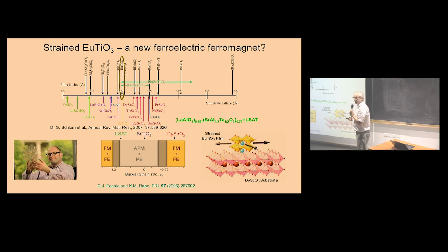In europium titanate, it's a similar story. It has a completely same crystal structure like strontium titanate. Lattice parameter is also completely the same, 3.90 something. And it has also antiferrodistortive phase transition, very similar things. But what is different is europium titanate is also antiferromagnet.